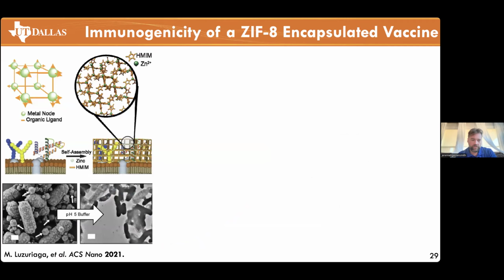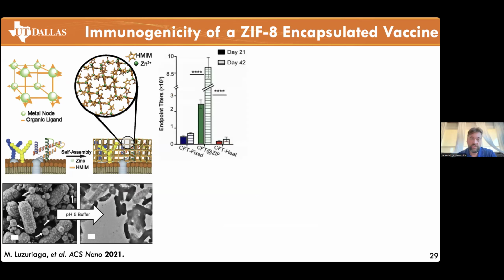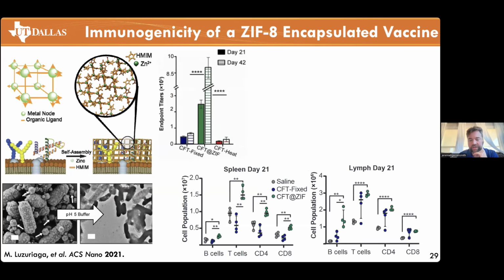Now, going back to our story on the bacterial infection, what we did was put the bacteria inside of a ZIF. When we did this injection and looked at endpoint titers at day 21, our ZIF formulation was already way higher in terms of total antibodies than the fixed version or the heat-treated version. We also benchmarked it against that. At day 42, it was an order of magnitude: we had 10 times more antibodies from our formulation than the more traditional fixed and heat-treated formulations. And that bears out not only in the lymph nodes.